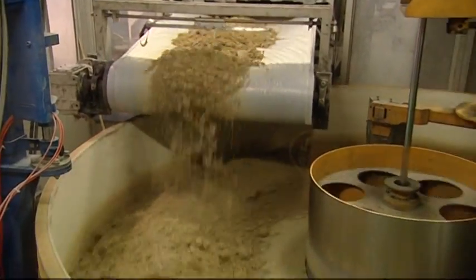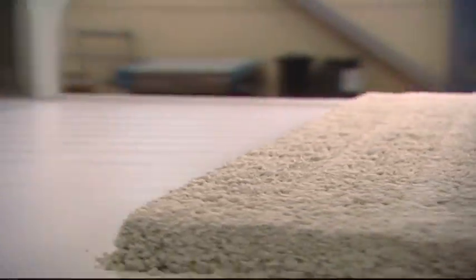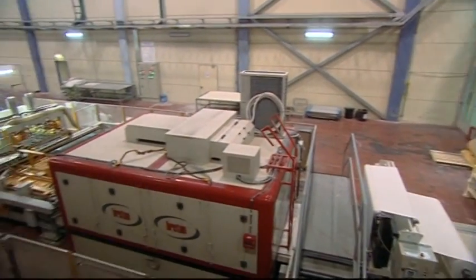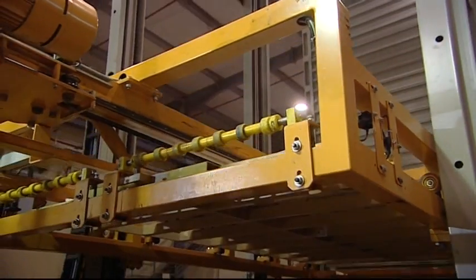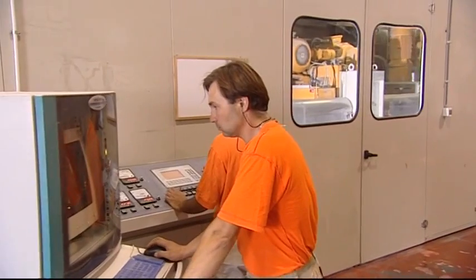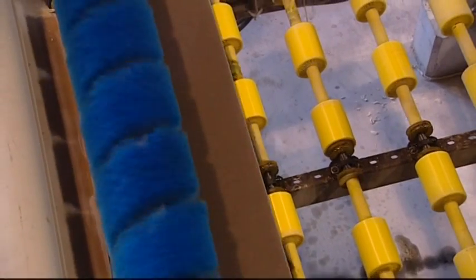During feeding and mixing, up to 93% natural quartz aggregates are blended with enhanced polymer resins and pigments. Poured into molds to form slabs, the mixture is compacted in a unique vacuum vibration process. In the curing kiln, Caesarstone receives its characteristic strength and solidity. The slabs are gauged and calibrated before being polished to the desired finish.